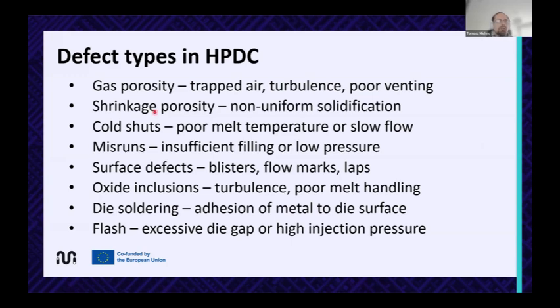is cooling down. There are also so-called cold shuts. It occurs when, for example, the temperature of the melted metal is too low in some areas. There are also misruns. So, for example, when the metal is not going to all small details in the mold, so there are some empty spaces, and also some other defects which occur a bit less in the process. And in this project, especially in this use case and in this paper, we focused only on the porosity.